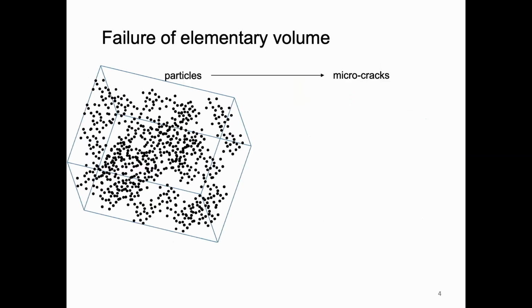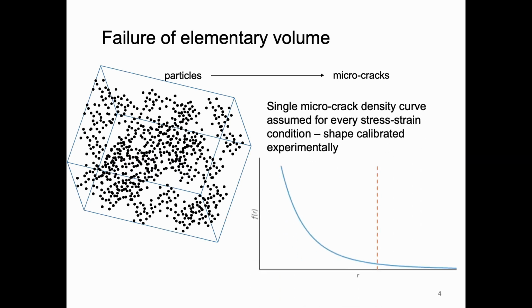And from there, the logic continues like that. You have second phase particles, which are initiators for damage. And some of them, not all of them, form microcracks. And then the local approaches say that the microcrack density curve is something that we don't know. We do know the density of particles that can be measured experimentally, but we don't know the microcrack density. And therefore, we assume that it looks like a power law. And then the shape of that power law is calibrated with experiments.